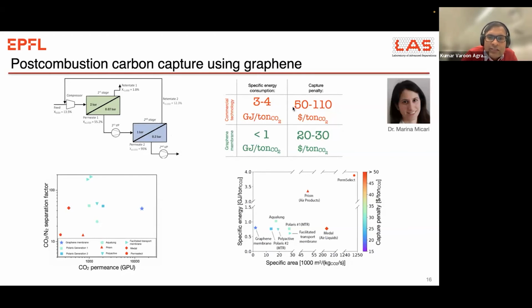And our latest optimization with these kind of membranes has shown us that while the commercial process, which is based on liquid amine, consumes down to 3 gigajoule per ton of CO2, with capture penalty at different concentrations of CO2 ranging from $50 to $110 per ton, we can reduce it by a factor of 2 to 3, so less than 1 gigajoule per ton of CO2, and $20 to $30 per ton of CO2 for capture penalty.